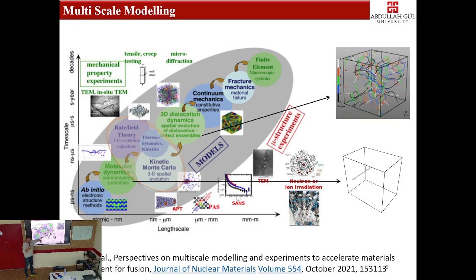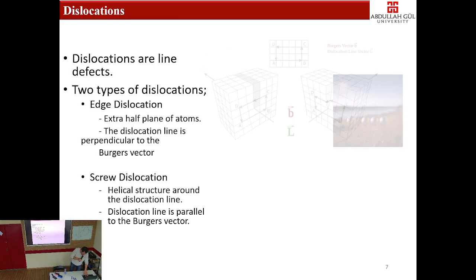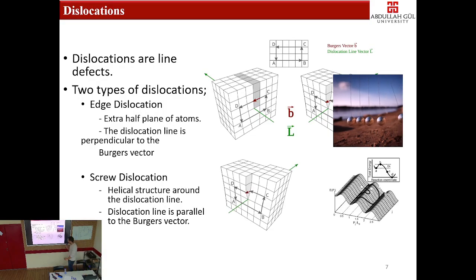In order to derive the mobility law of edge dislocation, we need to perform some molecular dynamics simulations at different temperatures, with different hydrogen concentrations. These are the main two inputs, with different stresses, of course. Let me go one more slide and check. I already explained what the dislocations are. So this is phonon drag. It's like a pendulum. The vibration of one atom also affects the vibration of another atom. They create the phonon, and we see phonon drag, edge dislocation, and boom, deformation.